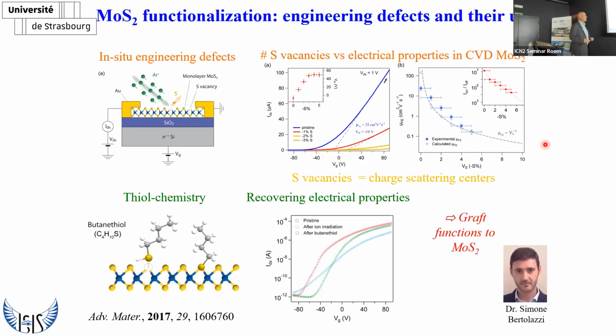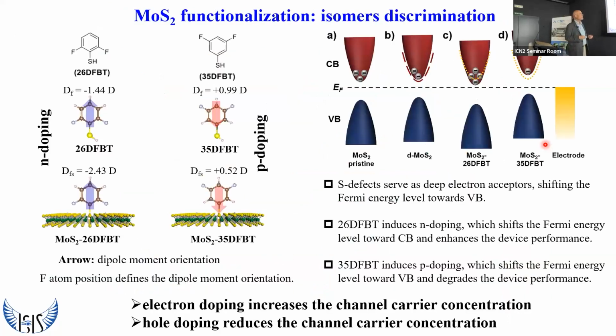Overall, we not only healed sulfur vacancies, but we can also use this to graft molecular function to the MoS2 when, instead of butanethiol, the molecule is a bit more sophisticated and integrates a functional unit. Now, just to give you an idea, this is a paper that has been submitted recently, so it didn't appear yet. The sensitivity of this kind of interaction and perturbation of the electronic state of the MoS2 is such that we have used it in this study to discriminate isomers. As you know, isomers are very complicated species to discriminate from the chemistry point of view, because these are molecules that have the same mass.